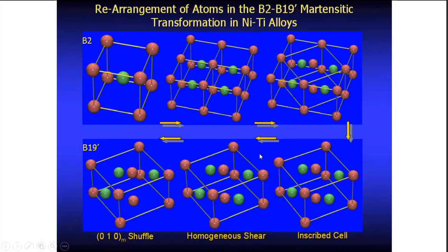And the final act which you have to do is that you see these 4 atoms that are here, 2, I think if I call it red and 2 green atoms, you have to just shuffle this face with these 3 faces. So you have 3 faces, which is the 010 plane. You just shuffle with respect to each other. And you can see this green has come in, and there's one green which has exited the space that was here. So what is happening is that this was the base-centered monoclinic, and now from the base center, it has moved away slightly, and it becomes a primitive monoclinic. So what you have done essentially is started with a primitive cubic and transformed to a primitive monoclinic, with a very small amount of shear and shuffle.